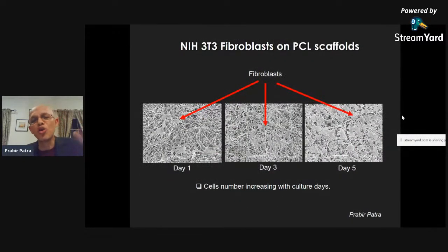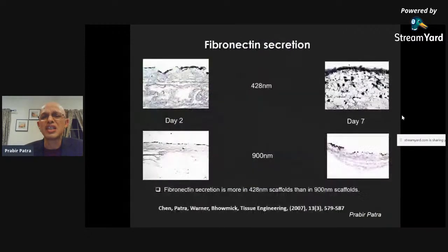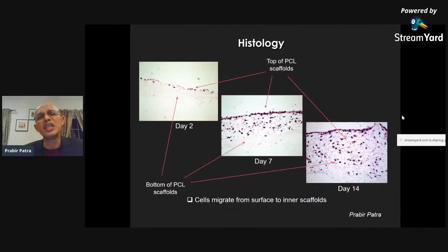Okay, so we played with all the parameters, and you can see this is where we started growing our own cells on these scaffolds. These are real skin cells that we got from NIH, fibroblast 3T3 skin cells. You can see day 1, day 3, and day 5, how they covered the entire matrix within 5 days. So these are the real cells you are seeing. We did a lot of analysis on how these cells grow. We did histology of various proteins, and we saw that from bottom to top, they cover the entire scaffold.